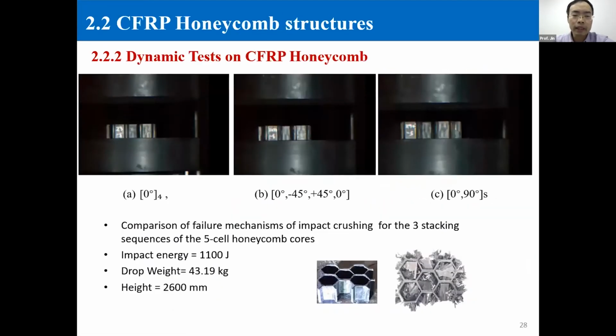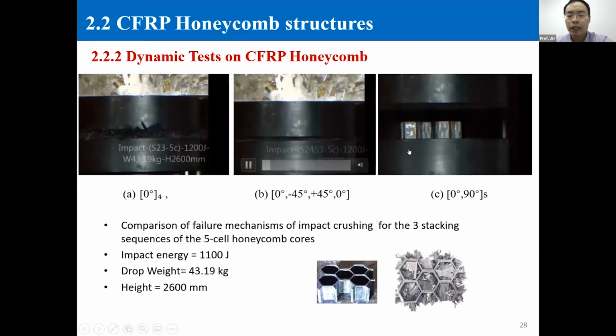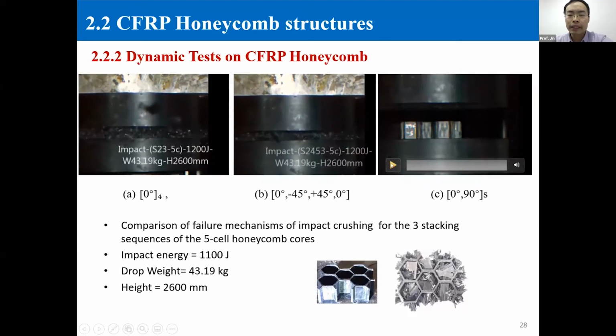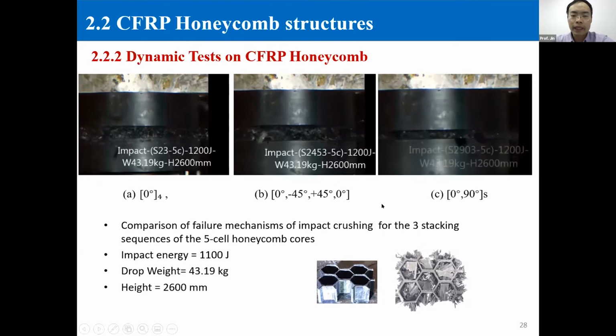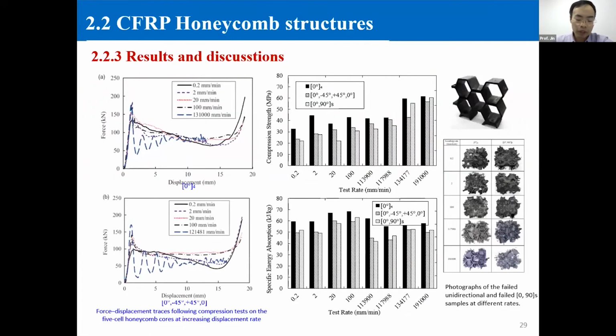From the test, this video shows the test on 3 different structures based on different composite layers. From this test, we can get the load displacement traces. The figure on the left shows that the structure was crushed at different loading rates from 0.2 millimeter per minute up to 133,000 millimeter per minute. We tested all 3 different structures and found the compression strength increased with the test loading rate, and the specific energy also increased, but it's nearly similar at various loading rates.